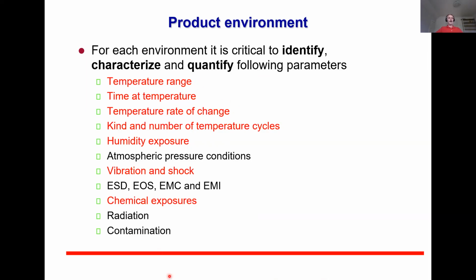So here I have marked or listed a few of those, and I wanted to put it so that the first 4 are somehow related to temperature. So first we have the temperature range. That means the typical and maximum minimum temperature and typical and maximum upper temperature. So that's the temperature range. Then we also need to know what is the time which the product is spending at certain temperatures. So for example, how long it is going to spend at temperatures above 150 degrees centigrade, above 100 degrees centigrade, below -40 degrees centigrade, and so on. Because